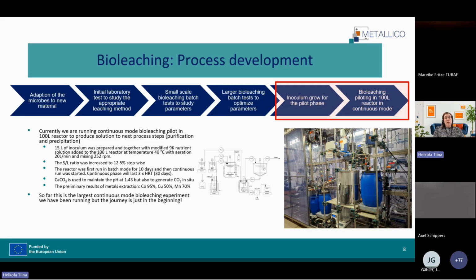And some preliminary results indicate that the metal extraction efficiency of cobalt is around 95%, around 50% for copper, and around 70% for manganese. In the end, it turned out that the nickel content in the material is insignificantly low. So of course we are leaching nickel as well, and then recovering it in the precipitation mode, but the concentrations are insignificant.